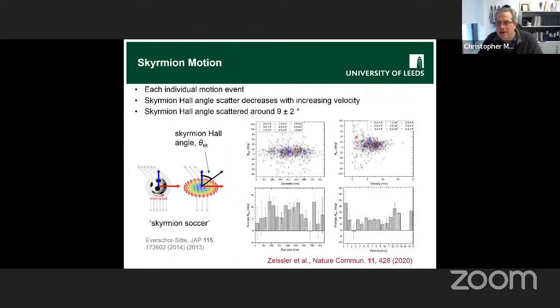And the way we sort of understood that is, well, some of these Skyrmions are quite free to move. So when you push them, they'll go quite fast. And they'll move with a Hall angle that's sort of their intrinsic value. And in fact, this sort of 9 degrees more or less fits what you'd expect for these kinds of Skyrmions. Some of the Skyrmions aren't very easy at all to move. So if you give them a push, they don't go very far or very fast, and they tend to move in a direction that's probably down some gradient in the energy landscape they're living in, rather than anything much to do with the driving force.